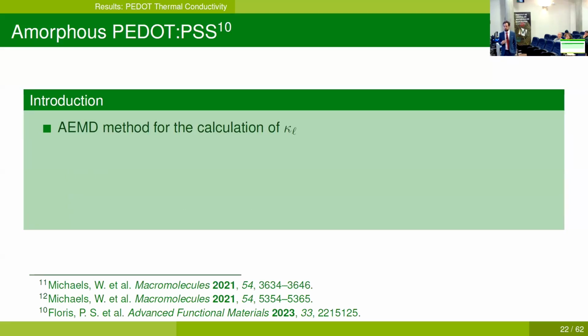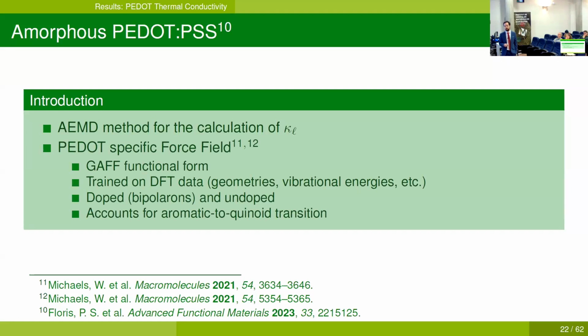So we have used the approach to equilibrium method for the calculation of kappa L, and we have used a PEDOT-specific force field that has the same functional form as GAFF, that is trained on PEDOT DFT data that is available in the literature. It is available for both its doped and undoped state, and it's specifically developed to account for the aromatic to quinoid transition.